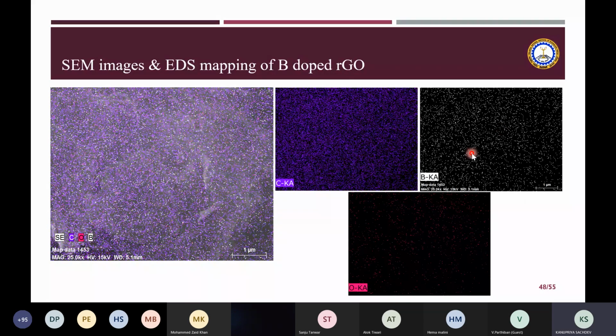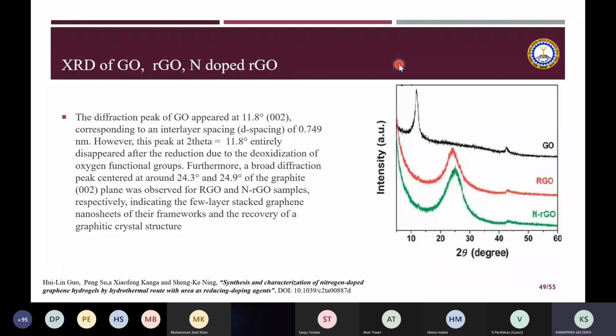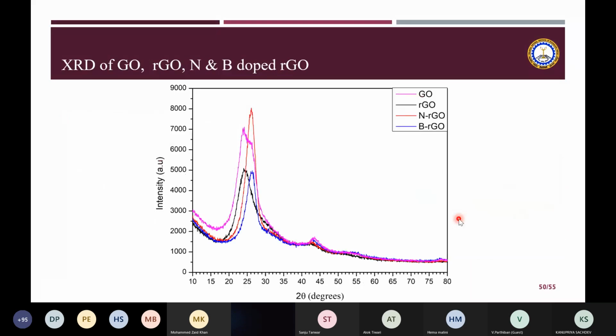So why were we doing this? We were developing these materials as electrode materials for the supercapacitor. And then we tried to have a look at asymmetric supercapacitors, that means one electrode boron doped and the other nitrogen doped, to see whether it was giving us good electrochemical properties. So that was the motivation behind it. And this gives the XRD, and you can see that with the presence of nitrogen in the RGO, the XRD peak is shifting. This is for all four: the XRD peaks of GO, RGO, nitrogen doped RGO, and boron doped RGO.